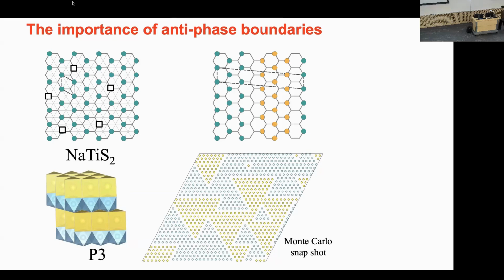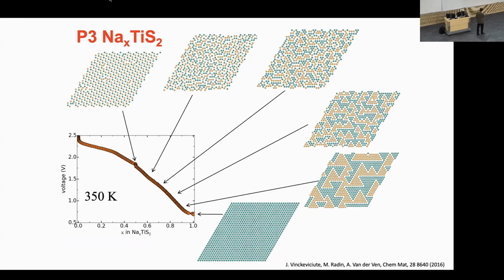And so as you remove sodium, this is a snapshot from one of the layers in a Monte Carlo cell of a big sodium TiS2 crystal. And this is at x equal to 1, all the sites are filled. And then you pull a few sodium out, so you leave some vacancies around. And instead of having randomly distributed vacancies, they all coalesce to form these, along these antiphase boundaries. You get this fractal-like pattern. And then you remove even more vacancies. And what you need to do then is, because you have more vacancies, you have to increase the total line length of these antiphase boundaries. And so that means you chop up these domains into smaller domains so that you increase the total line length, and you continue to do that. And so you have a very different form of creating entropy than that of just randomly distributing vacancies on a lattice. It's more of a kind of a fractal entropic kind of accommodation of these vacancies.